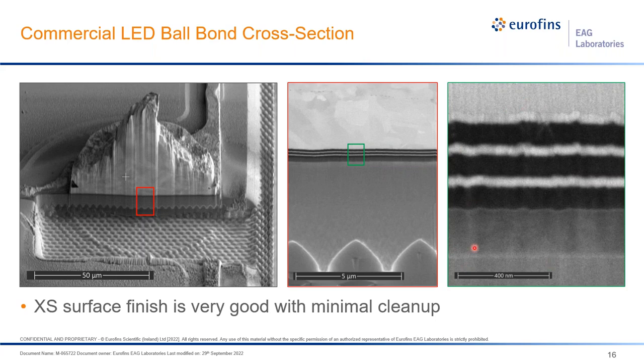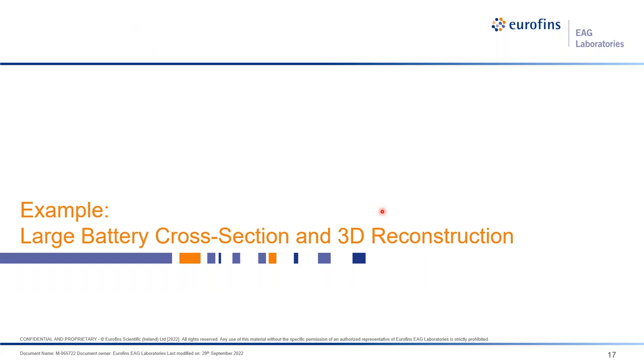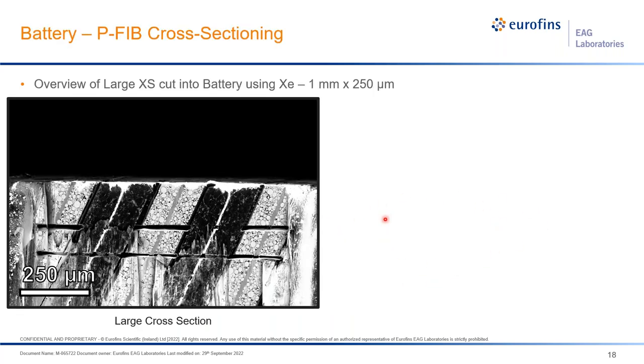So the thing to take away here is that you can make these very large cross sections, but the cross section surface finish is very good with fairly minimal curtaining, et cetera, very deep down within the sample. So then that leads us to, let's take a look at an even larger cross section, in this case, a battery cross section, combined with the ability to then do 3D reconstructions from cut and look data.